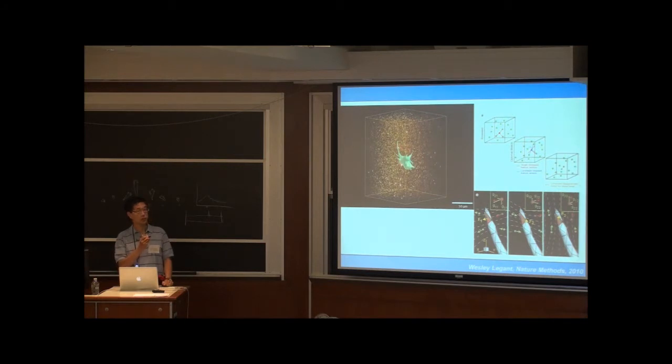So we have to track those beads, and of course this is a little bit more challenging because now we have to do confocal stacks throughout this structure, this volume, to find where all the beads are. And if we want high resolution, we need more beads, and we have to do finer stacks. Once we have all the beads, you can imagine in a stressed state, you have beads in a certain position, and to de-stress them, to find out where the zero stress state is, on a 2D gel, the way you do that is you detach the cells. So the cells are sitting on a surface, they have certain bead positions, you detach the cell, the beads all move, and now you know the zero stress state, right?